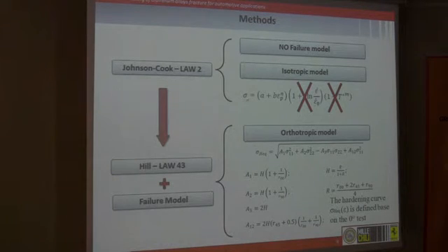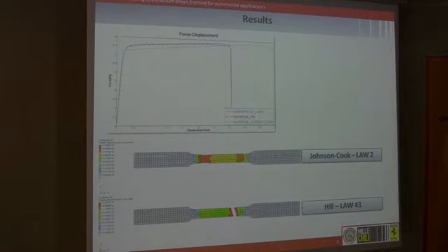Since Hill's yield law is based on the stress state only, it's not possible to directly define the orthotropy in terms of strain. By supplying a suitable material card per set in terms of the Lankford parameters, along with the stress strain curve of the 0 degree specimen test, it's possible to reproduce the multi-axial and resulting material behavior.